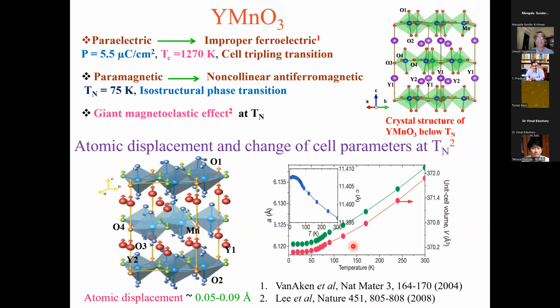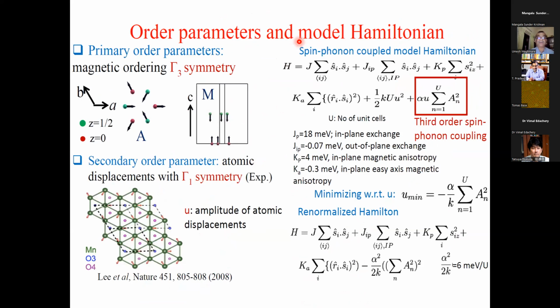Okay, so this was quite exciting, and I don't think it is understood how this happens, although there are two very interesting papers published on this effect. So we used our approach. Again, I won't go into details of it, but it involves the same sort of steps. In this case, instead of phonons, we work with the spin on the manganese site, and we consider various orientations of spins. These are called magnetic orderings with different symmetries, and we calculate their energies.